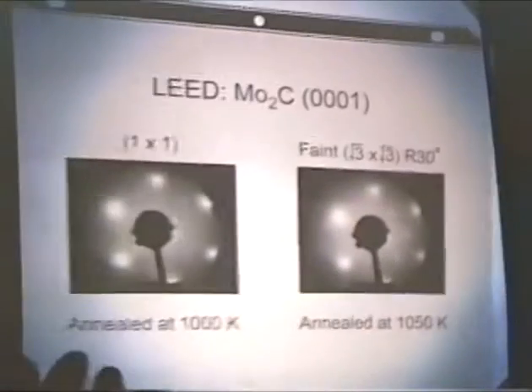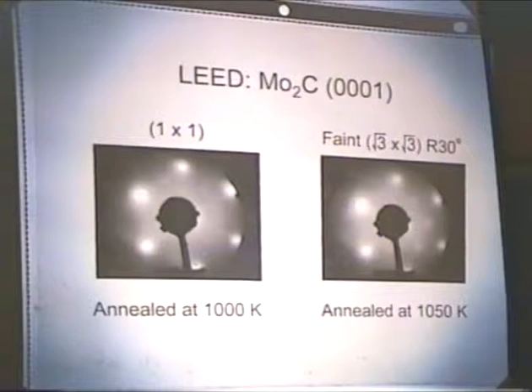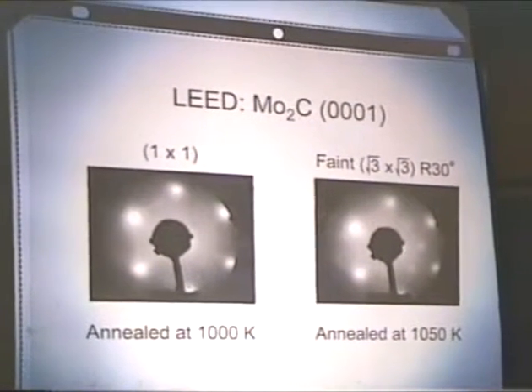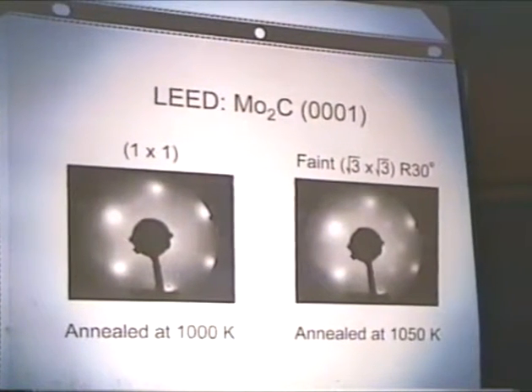So for this study today, we're confined then to annealing temperatures of 1000 Kelvin or lower. 1000 Kelvin is what we've used as a standard surface preparation. These are a couple of LEED results, and I'd just like to show that this is on a sputtered surface annealed to 1000 Kelvin, and you see a consistent one-by-one LEED periodicity.